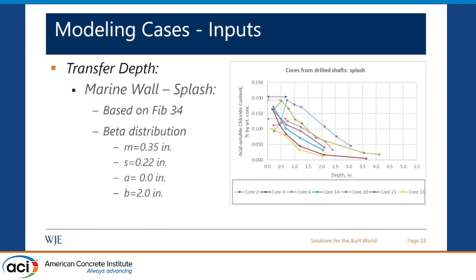So this is similar to what is presented in Fib 34. And Fib 34 gives you a distribution to use for that transfer depth function. So it gives you a beta distribution with an average value of 0.35 inches. And we validated that through lots of investigation on actual marine structures. I'm showing a few profiles here, but while doing this work, I looked through 3 different projects that we did before, so more than 30 chloride profiles, and based on that, the Fib 34 distribution is a good representation of that transfer depth. However, when I looked at those profiles, there are many of them that still show a diffusion-based chloride profile. So it's on the conservative side to use the Fib 34.